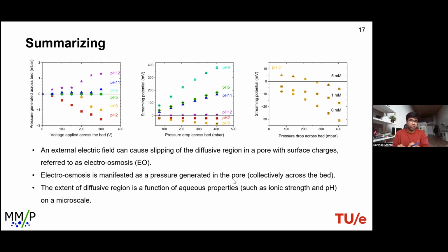To summarize, the electric field responsible for electroosmosis is essential, but so are zeta potential and ionic strength. While zeta potential is important to create the diffusive region, it is actually the ionic strength that leads to electroosmosis or water migration under the electric field. As we increase the salt concentration, we reduce the Debye length, increase the ionic strength, and see better electroosmotic dewatering, which I cannot, of course, show in these experiments so far.